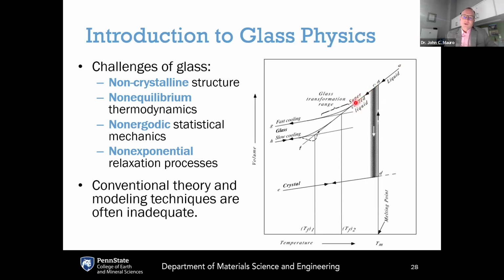And if you take that supercooled liquid and continue to cool it, the viscosity continues to go higher and higher. So it becomes less and less fluid. It takes longer and longer timescales for it to flow. Eventually the timescales for it to flow become much longer than our timescales of observing the supercooled liquid. When that happens, it undergoes this so-called glass transformation range or glass transition range, and you get a freezing in of that supercooled liquid structure.